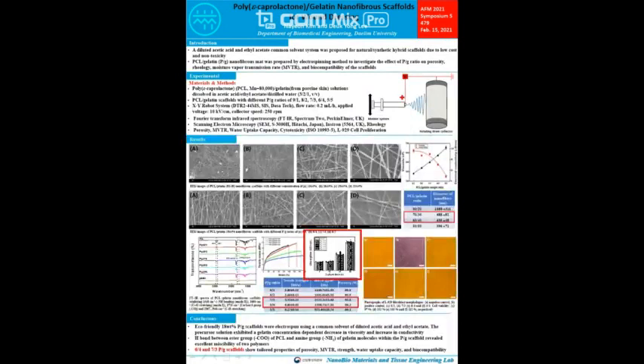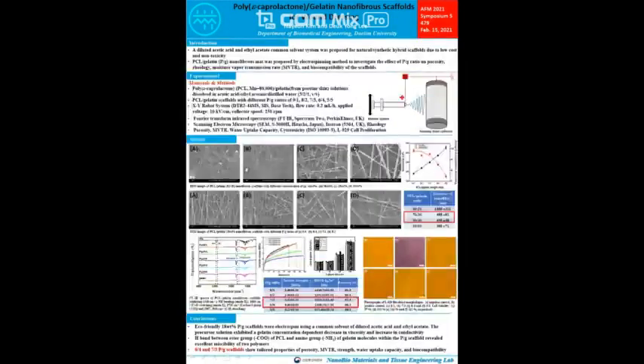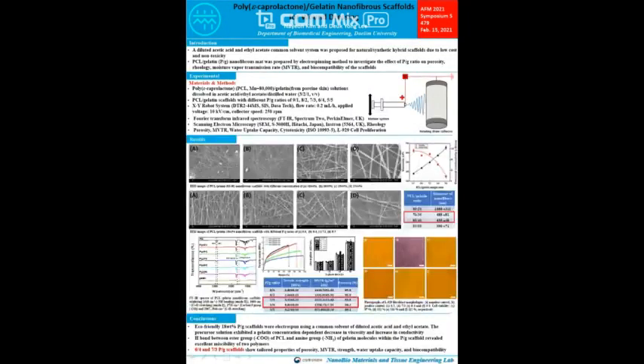The proliferation results of L929 cells indicate that the PG scaffold continued to proliferate over time regardless of the gelatin ratio. Therefore, under the conditions of this study, the PG scaffold is non-toxic and has excellent cell proliferation, so it can be used as a wound dressing. When all the results of the above experiments are combined, scaffolds in the range of 6:4 to 7:3 PG ratios are considered the material of choice for wound dressing due to adjustable properties of morphology, MVTR, tensile strength, cell viability, and proliferation.